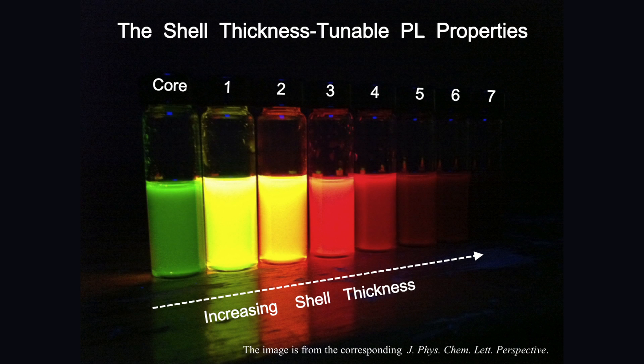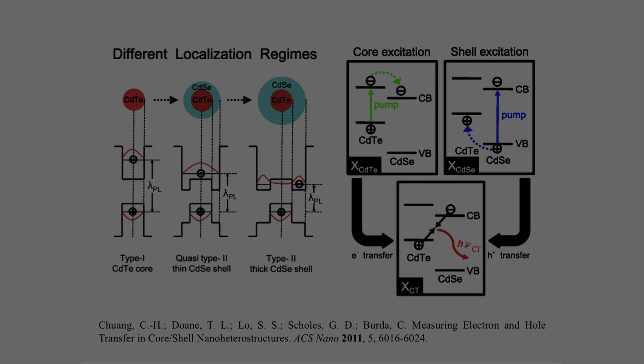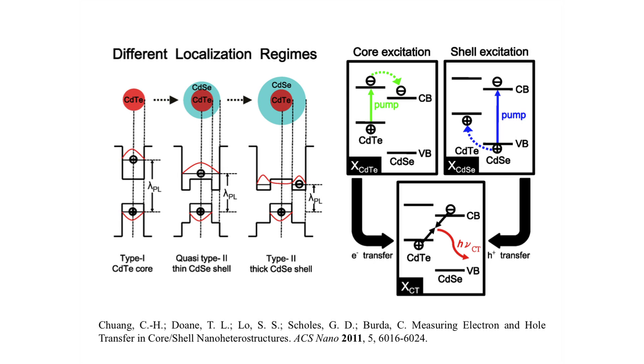I synthesize a series of core-shell quantum dots with increasing shell thickness. With increasing shell thickness, we observe the transition from type 1 to quasi-type 2 regimes.